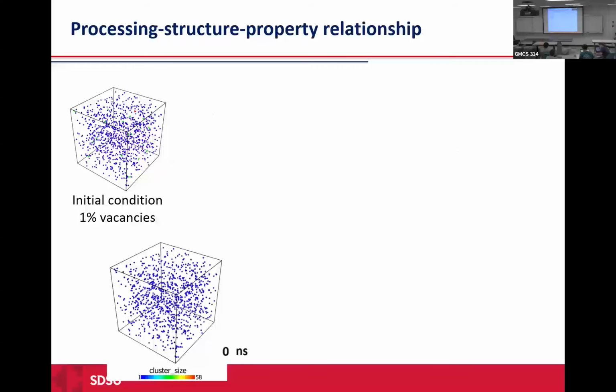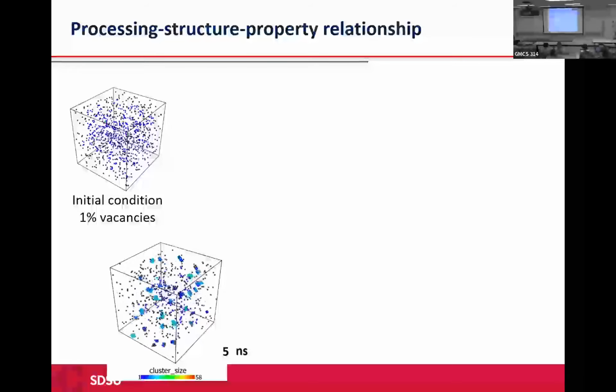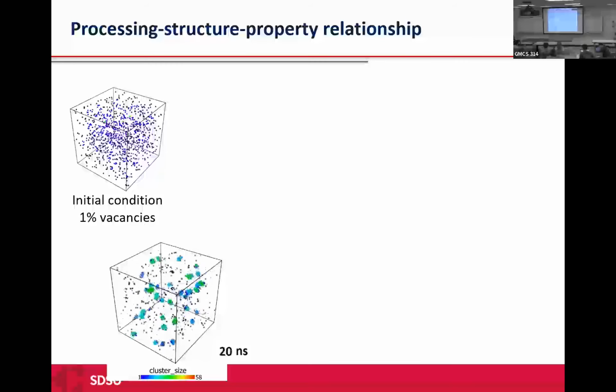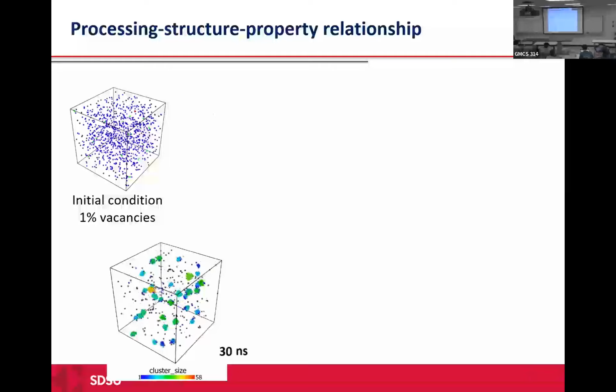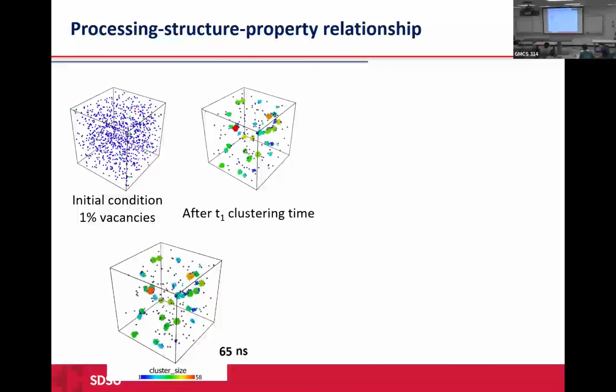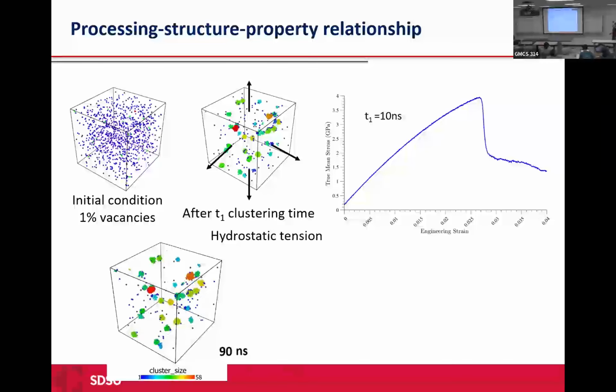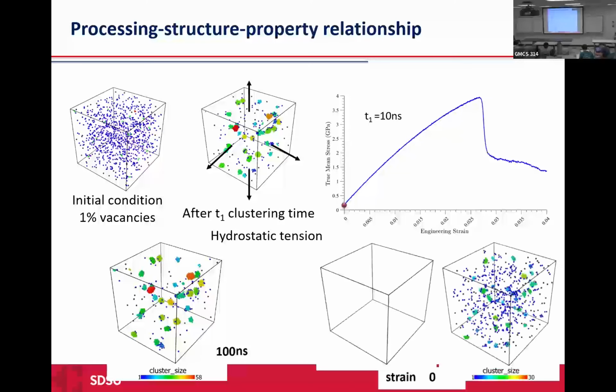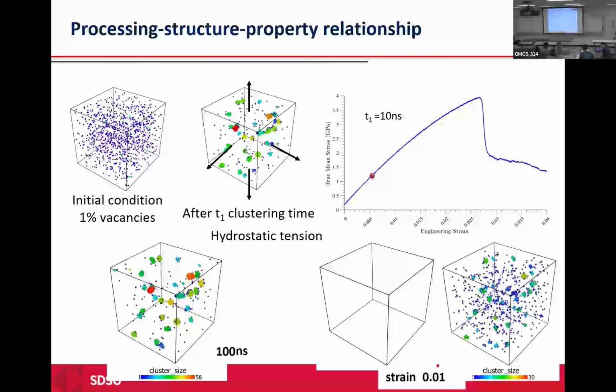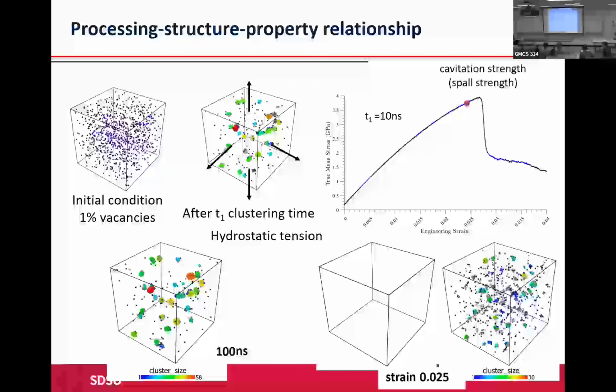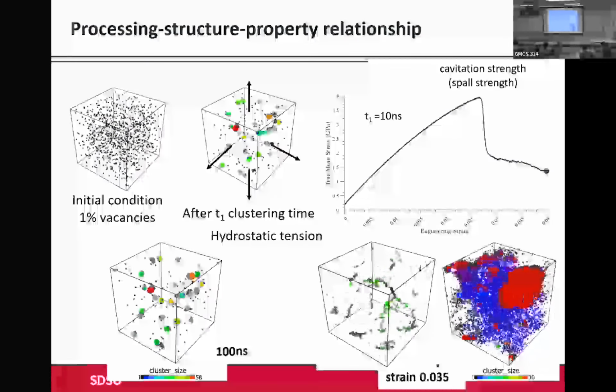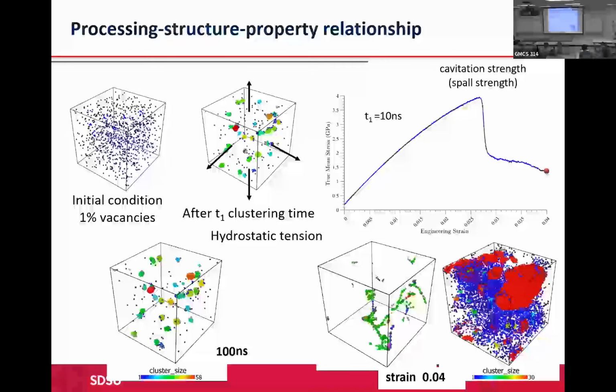Okay, just visualize the process. We have started with the initial condition, just removing 1% of vacancies and giving the structure time to evolve, and then we can see that those vacancies are clustering together. At each different time step, we are applying hydrostatic loading to the sample and then drawing a stress strain curve for the material to see how the material would fare and what the spall failure is, which is the maximum stress of the material through the simulation.